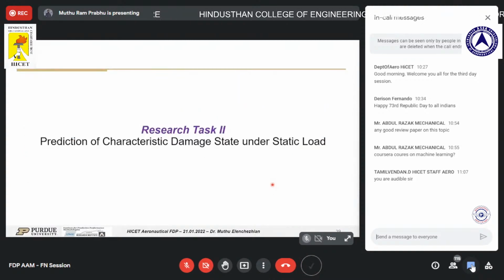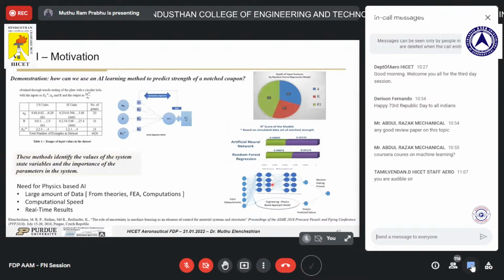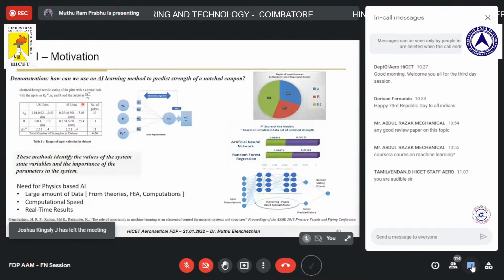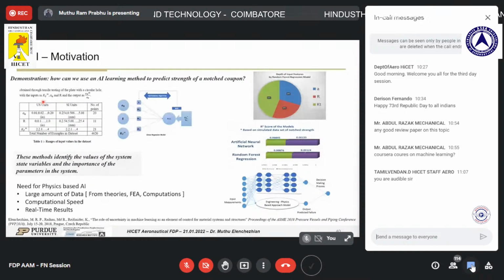The next task I'll be speaking about is how to identify the damaged state. How we started this work was, we first took a physics-based equation, similar to the AND gate example. We took the relationship to obtain the notch strength of the composite material, sigma n divided by sigma naught. The notch strength is developed based on three input factors, which are KT, A naught, and R. Based on these three values, we have a physical relationship which has been established, and we generated an artificial data set, developing random input values for all three parameters, obtained from statistics and the literature, and developed the data set.